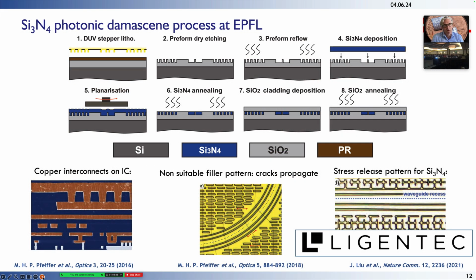And so the way we, in my lab and also other labs, have overcome this is we have introduced a new manufacturing technique. And instead of manufacturing by depositing films and etching them, what you would call subtractive processing, what we have done is we have taken a very well-known material, which is an oxidized silicon wafer, and etched a preform inside that for the waveguide. And this preform hosts the waveguide material. What's the advantage here? The advantage is we do not have to etch silicon nitride. We can directly deposit into the preform. We can make stress release layers to avoid that cracks propagate. We can then perform planarization, so CMP, place a cladding on top, and make waveguides that are as high as 1 micron without suffering from crack formation.